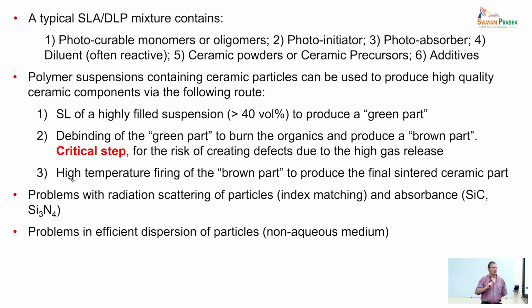In any case, coming back to VAT photopolymerization technologies, some of the issues that you have when you are applying these technologies to ceramic-based feedstocks, especially conventional ceramics using powder-based systems: you have problems with certain materials because of radiation scattering from the particles, so you do not have a good index matching between the ceramic particles and the photopolymer. Typically, the ceramic particles can have a refractive index much higher than that of the photopolymer. Or you have issues in terms of the fact that your particle absorbs. So for instance, silicon carbide, which is a very interesting and useful ceramic material for high-end applications, cannot be typically processed using this approach.